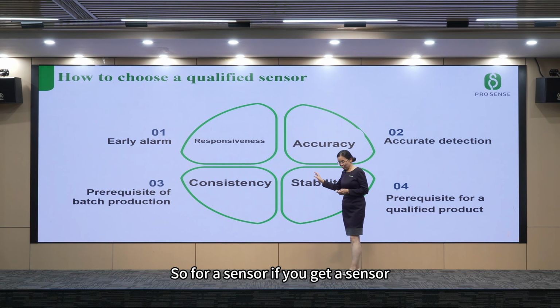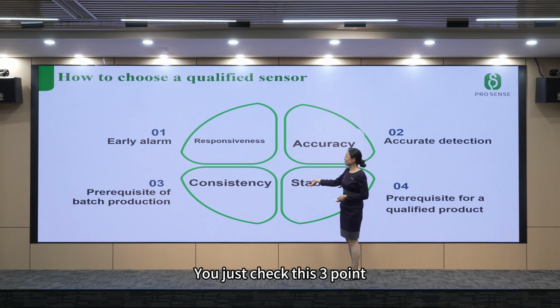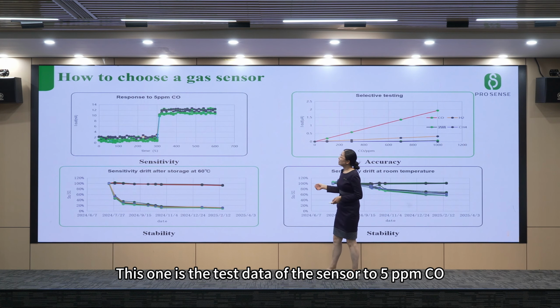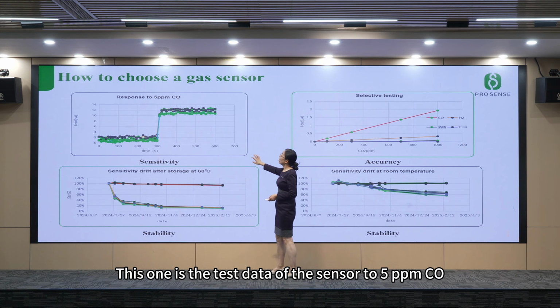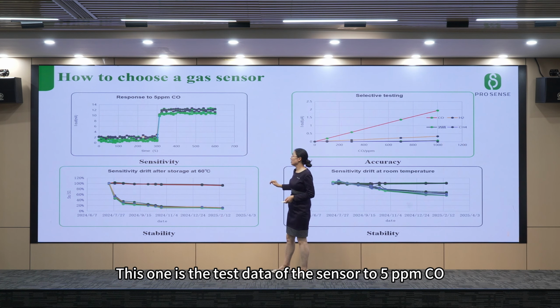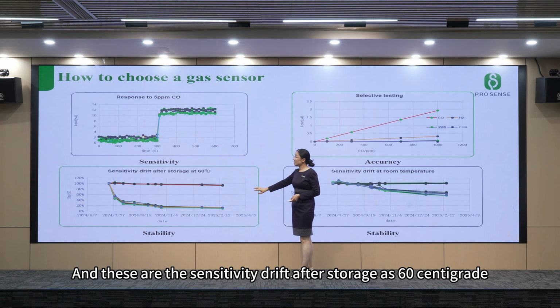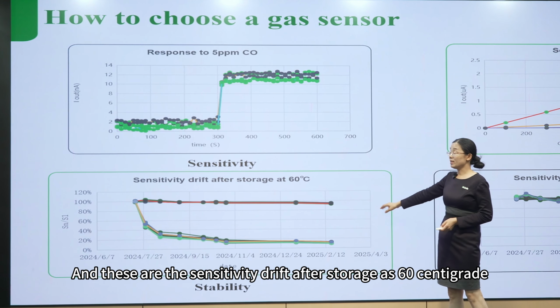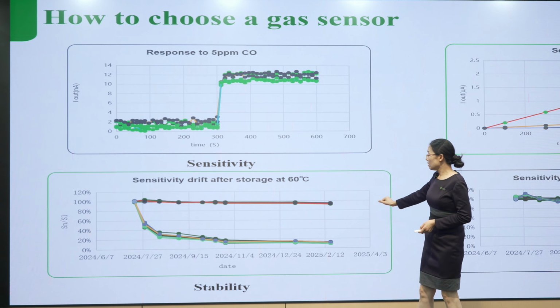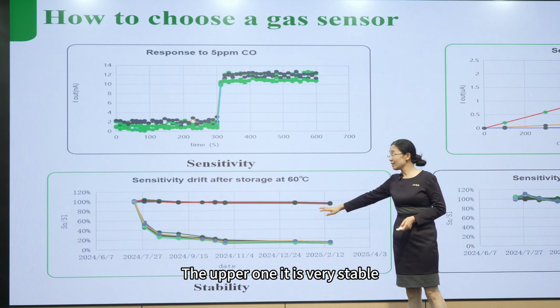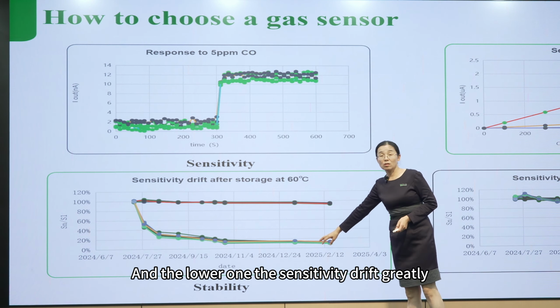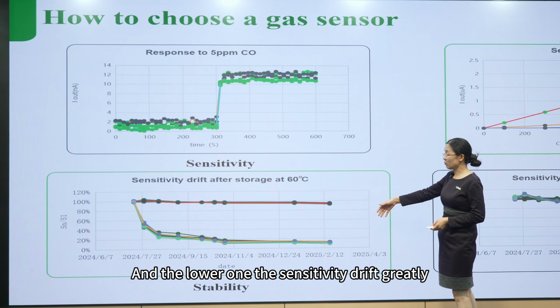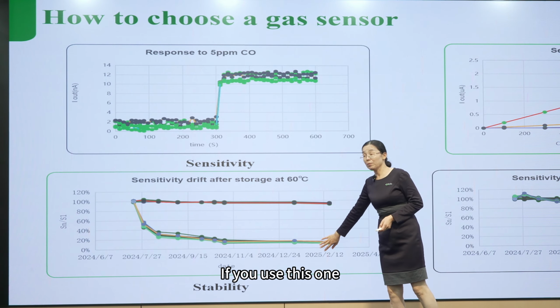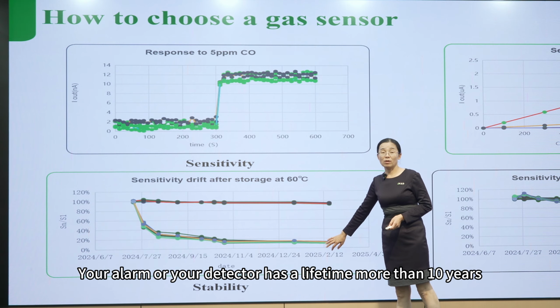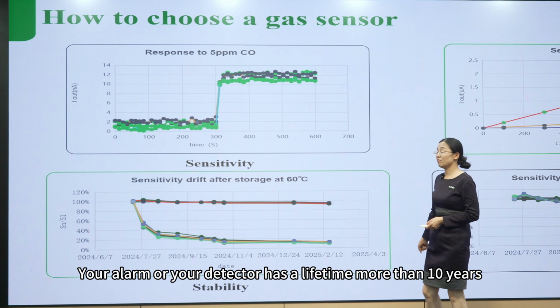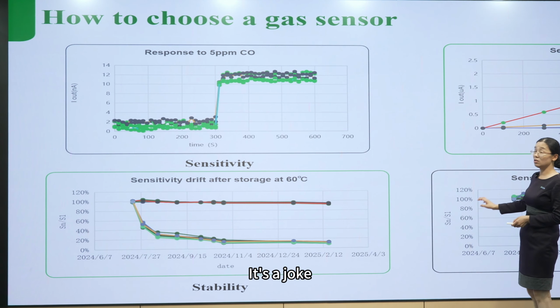So if you get a sensor, you just check these 3 points. This is the test data of the sensor to 5 ppm CO, showing the sensitivity drift after storage at 60 centigrade. These are 2 sensors. The upper one is very stable, and for the lower one, the sensitivity drifts greatly. If you use this one, how can you say that your alarm or your detector has a lifetime of more than 10 years? It's a joke.